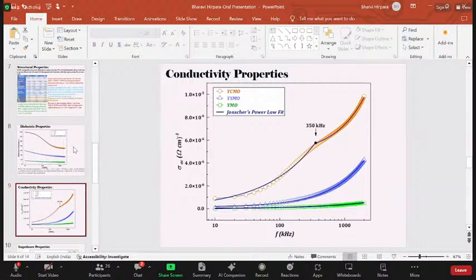Whereas for YCMO manganite compounds, two different conduction mechanisms have been seen. As we can see, Jonscher's power law fits in two different regions, one at the lower frequency region, well below 350 kilohertz, and the other above the same. Interestingly, the obtained values of eta for all the samples are lower than unity, which indicates the presence of a correlated barrier hopping mechanism for the charge conduction process.